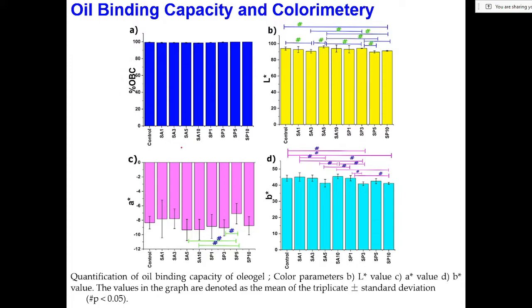In all of these oleogels that we have used, we found that the oil binding capacity was more than 99%. That means the addition of the emulsifiers to the control system has not altered the oil binding capacity. Okay. However, when we analyzed the color of the samples, we found that there were certain changes in the color parameters. In colorimetry, there are three parameters which we have determined: L star, A star and B star.